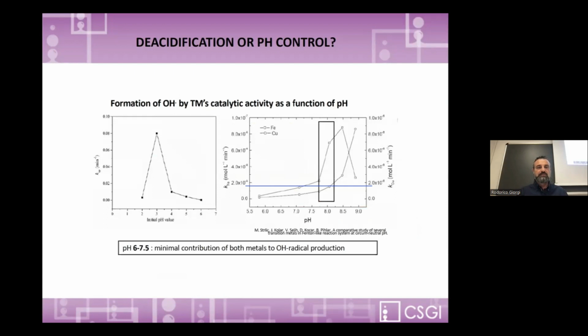And this paper by Matthias Strlič and Jana Kolar is very, very important because it focuses for the first time on the importance of pH in the inhibition of this catalytic activity. For example, it is well known that in acidic medium we have the activation of this Fenton reaction, but we also have such activity if we go at higher pH, higher than 8.5 in the case of iron, and even less in the case of copper, that sometimes more than expected is present as a contaminant of iron gall ink. So looking at these two experimental data provided by Strlič and Kolar, we realize that neutrality is the best condition in order to inhibit OH radical production.